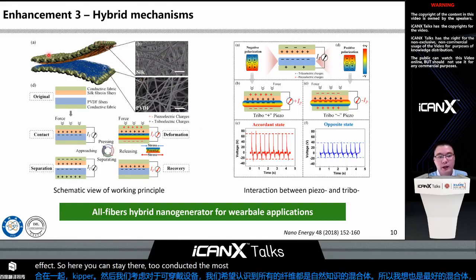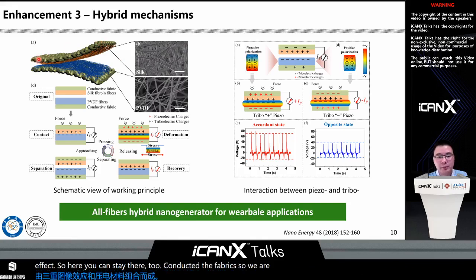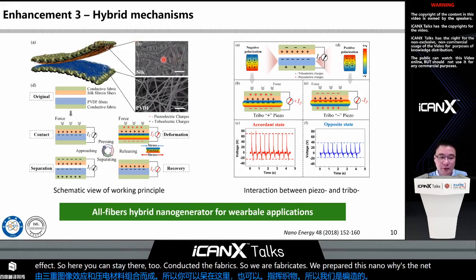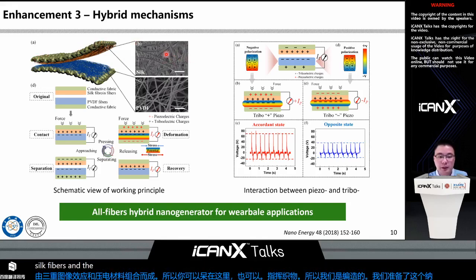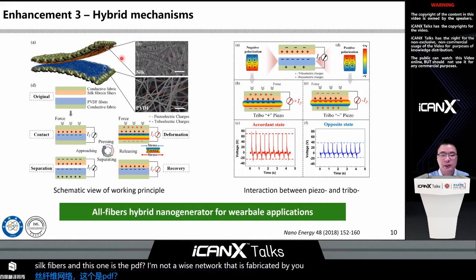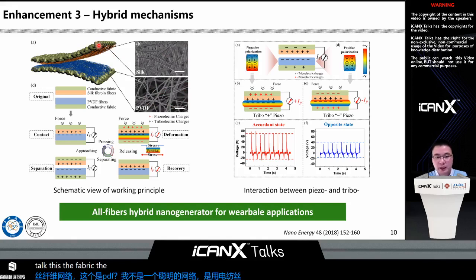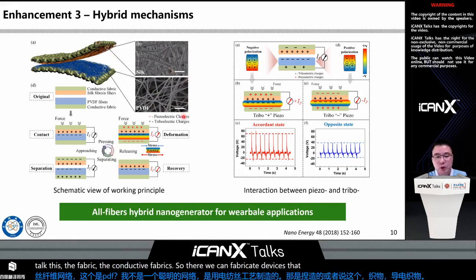We prepared the nanowire network of silk fibers. And this one is the PVDF nanowire network, fabricated by the electrospinning process on top of the conductive fabric. Then we can fabricate the device in the form of all fibers.